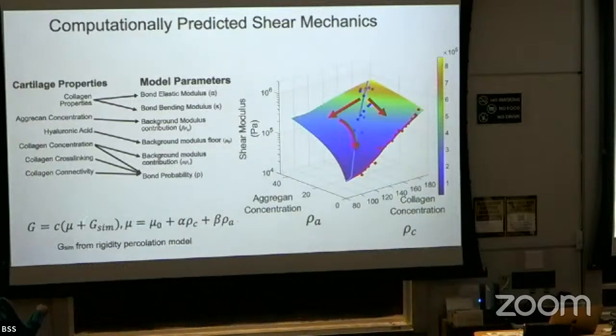So this G is, we are getting this from the rigidity percolation thing, right? And this will have a rigidity percolation kind of dependence. So it's not a linear something, right? At the percolation threshold, this is going to go to 0, even with all the constraints, right? But in reality, for your tissue, your G is not going to go to 0 at a certain concentration because you are setting a background floor because of the presence of all of these materials. And this part is taking care of all of that. But this part also changes as a function of tissue depth. The hyaluronic acid part doesn't, but the aggrecan part and the bits of collagen that are not in the network are both going to change as a function of tissue depth.